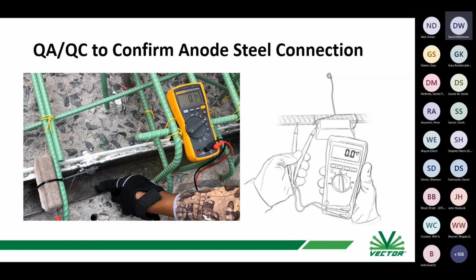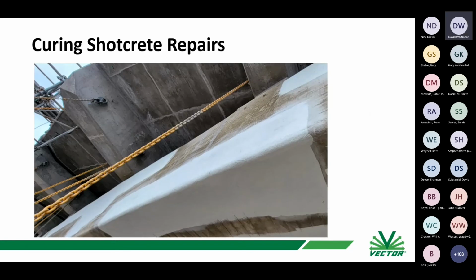If you use copper wires, you have to be very careful about insulating those connections where you're connecting copper. Copper wires are great, they're good conductors, but then when you're connecting between the copper and the steel, you're going to make a dissimilar metal connection there. And if that connection isn't perfectly coated with epoxy, then it's pushing things the other way, because the steel is going to become the anode to that copper wire, right? And then you run into the same thing sometimes if you have copper grounding systems that are embedded in foundations and things. Like all of this happens. Terrible. This is all about electrolysis. This is all electrochemistry.